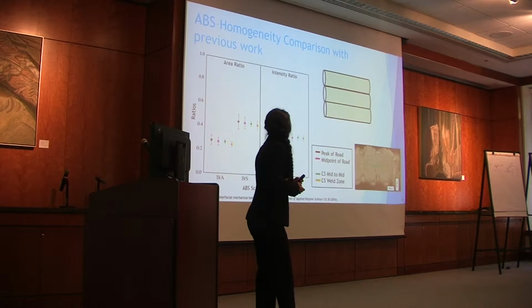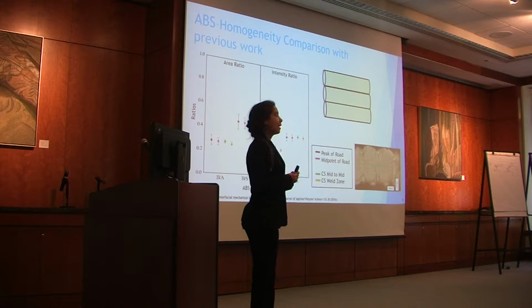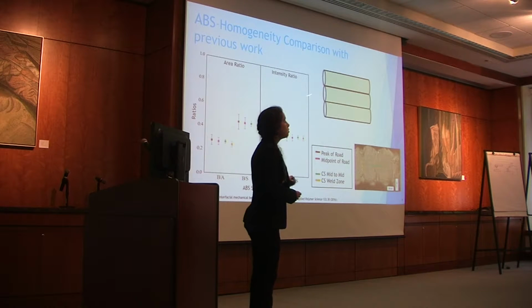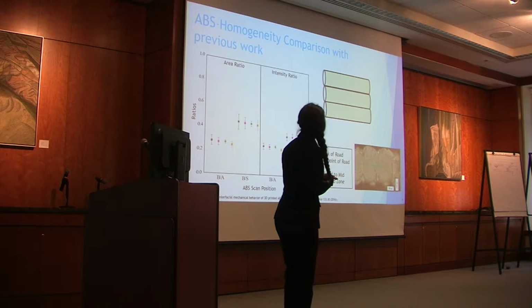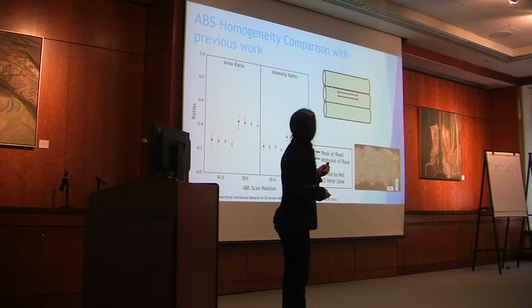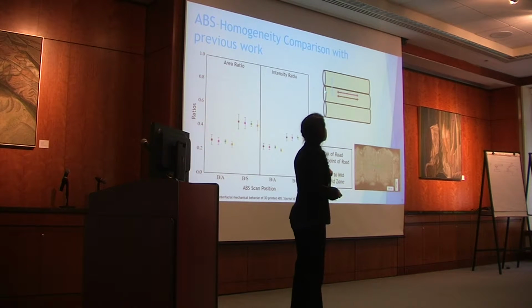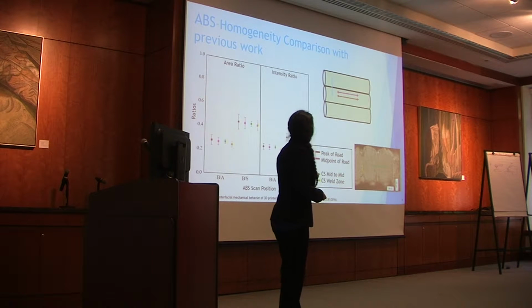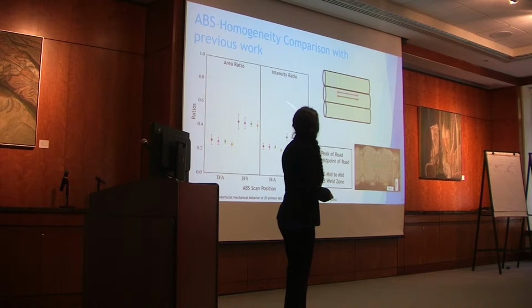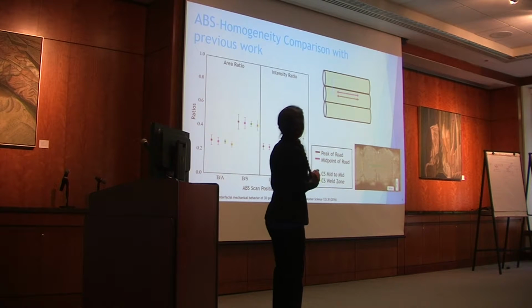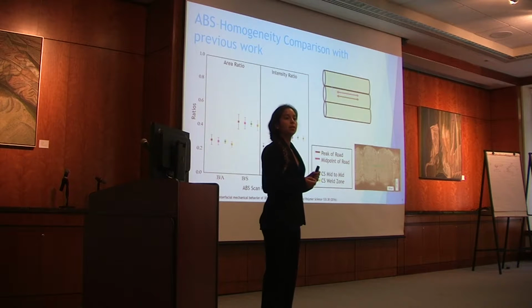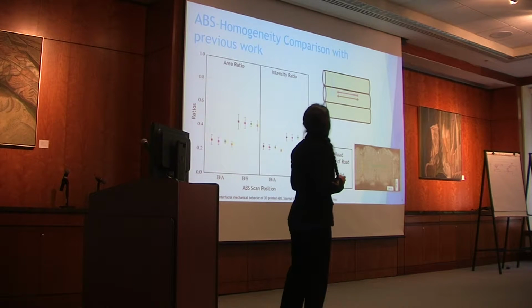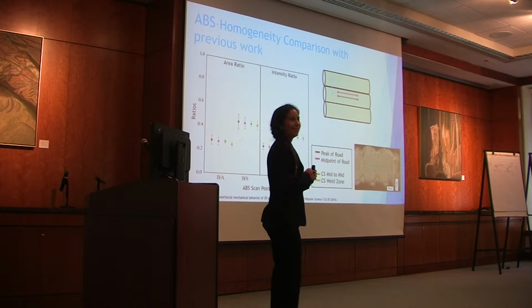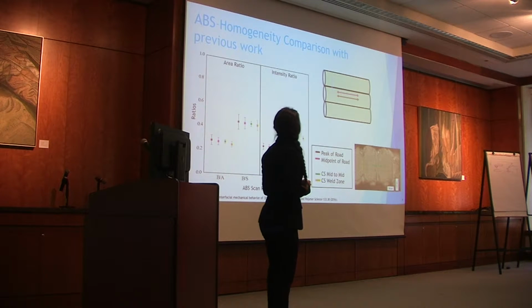So this is a nice little graph. Like I said, I did mini scans, and with this, I was able to develop an average of the relative ratios, and these are error bars. With my scans, like I said earlier, I went and looked down these roads. In previously published work, they looked through the roads in some sense. As you can see based on my graph here, we were able to determine that all these samples were homogeneous based on many, many data points and many, many hours on the Renishaw.